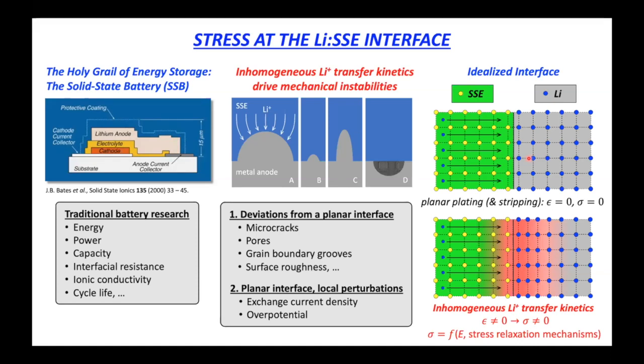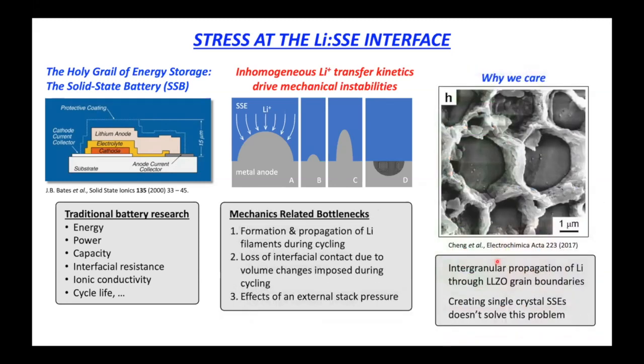The problem we have to deal with, though, is that these lithium-filled interface defects create this non-uniform plating, and that's going to give us this gradient in the lattice parameter here. That gradient in the lattice parameter creates a local gradient in the pressure, right? And the magnitude of that pressure is going to depend on the elastic modulus of the lithium within this localized volume of material. It's also going to depend on the stress relaxation mechanisms that are available to operate, not only within the lithium, but of course over here on the other side of the interface in the separator as well. So in broad brushstrokes, that's what the basic problem is for us and how we have to think about trying to solve it.